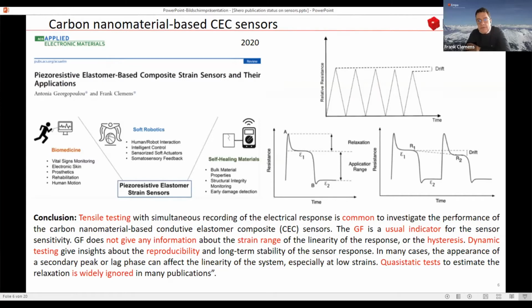Unfortunately, if you look in the literature, as I already mentioned, very often people look at this kind of hysteresis. They run a lot of dynamic experiments for reproducibility, to measure the gauge factor. This is what you see in 99% of all the papers. But the quasi-static tests are very heavily ignored in many publications, even though if people did this, they would see that their sensor may not be as good as they propose.